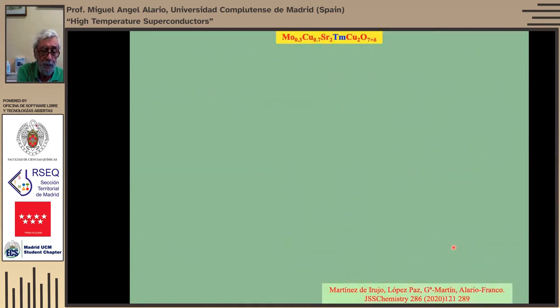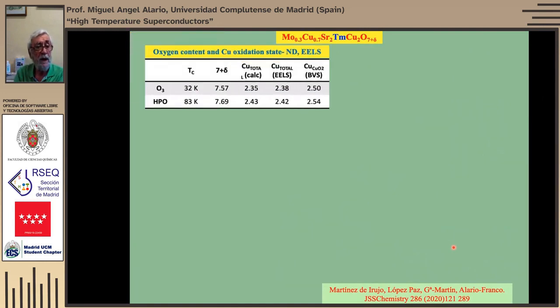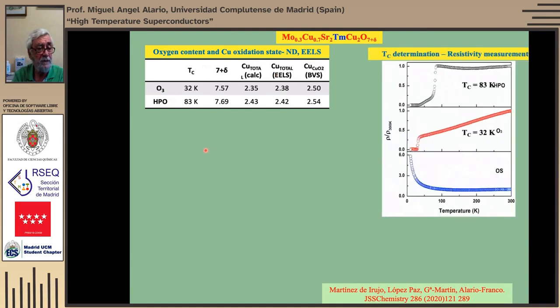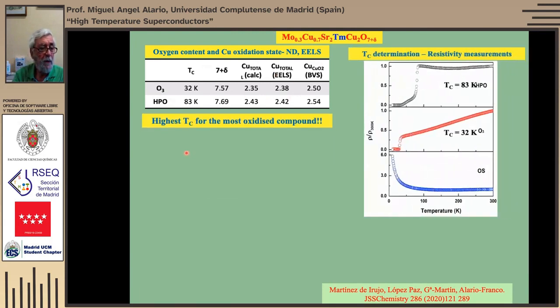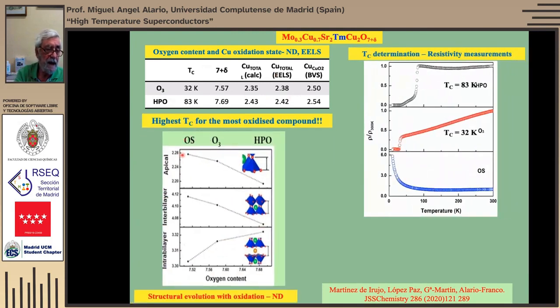So we have tried to emulate this in the work of Susana Lopez and Xavier Martinez de Irujo, and we have been able to, by oxidation, instead of using a pulse, make it a permanent thing. So we use the chemical reaction. So we use ozone oxidation of this material, and then, well, we get the apical distance. You see that it decreases. The interbilayer decreases and the intrabilayer increases. So exactly the same as before.